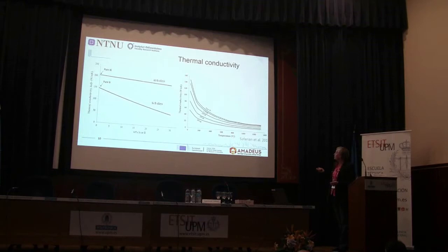It will also decrease with temperature. If we look at the thermal conductivity, this is pure silicon with increasing amount of boron. So we see that with temperature it goes down. The thermal conductivity in the area where we are interested is in the area of 20 watt per meter Kelvin. And with increasing amount of boron, it is actually lower.